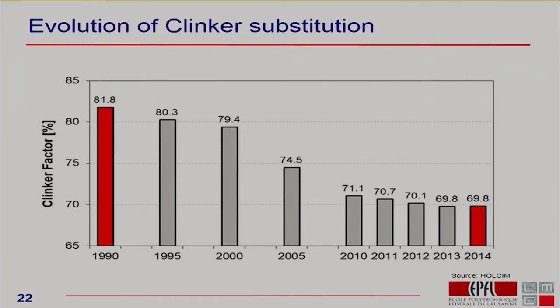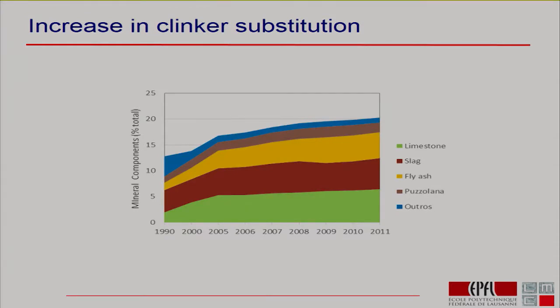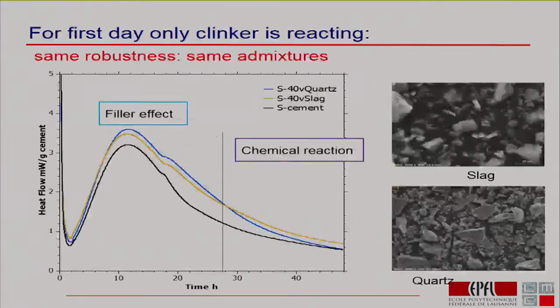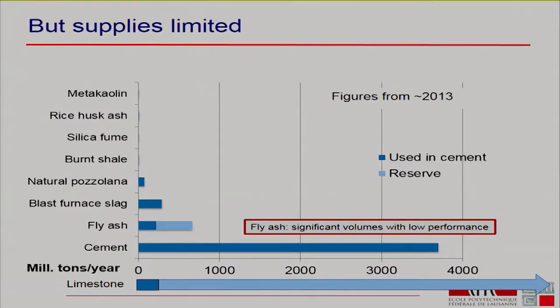There's been very little progress in the past 5 or 6 years, and these are the worldwide figures from a lot of cement companies. And we see that at the end of the day, we're really talking about 3 products. We're talking about limestone, we're talking about slag, and we're talking about fly ash. This makes up more than 80% of the materials we blend into concrete. So why is it slowing down? I'll come back to that. It's slowing down because the amounts of these materials we have are in fairly short supply compared to the colossal amount of cement we need.